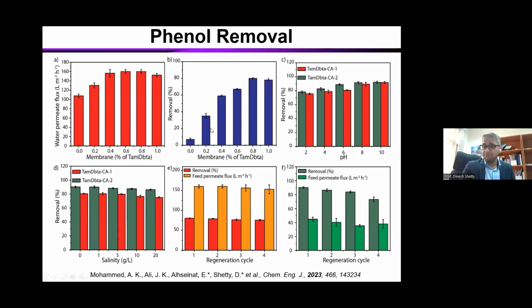Then we used this membrane for the phenol removal. As you can see, with 0.8% there is a saturation, even if you increase the amount of COF. With just 0.8% of COF as a pillar, we were able to get 82%. But the drastic difference is that with the cellulose acetate membrane, you are not getting much. Then we did all this with different pH conditions, because we are talking about different water sources with different pH and different salinity. This is very important because we tried using this material for water coming from oil refineries, because when you're digging oil, you end up getting this mixture of water with phenol. So that's what we did.